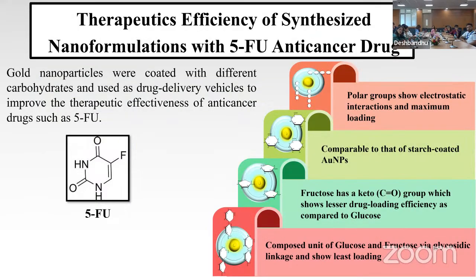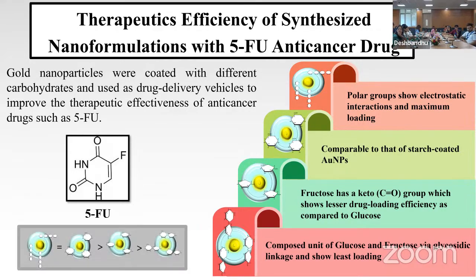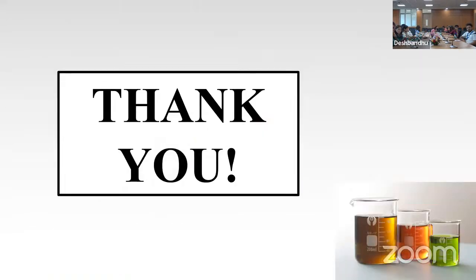Now to calculate the therapeutic efficiency of the synthesized nanoformulation, a drug loading study was performed with the 5-fluorouracil anti-cancer drug. The trend observed for therapeutic efficiency is that starch and glucose give similar therapeutic efficiency. The drug loaded starch and glucose are approximately the same, then fructose, and the drug loaded sucrose coated gold nanoparticle has the least loading. Thank you.